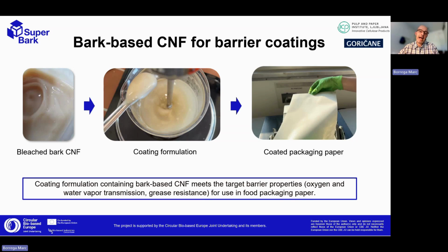This is added in a formulation containing another bio-based polymer, and after mixing, you use the formulation to coat packaging paper. The work has been done, or is being done, by our Slovenian colleagues from the Pulp and Paper Institute in Ljubljana and Goricane. They're working together on this. They have been measuring all the barrier properties which are relevant for the final application, which is food packaging. They have been testing oxygen transmission, water vapor transmission, grease resistance, and also mechanical properties.